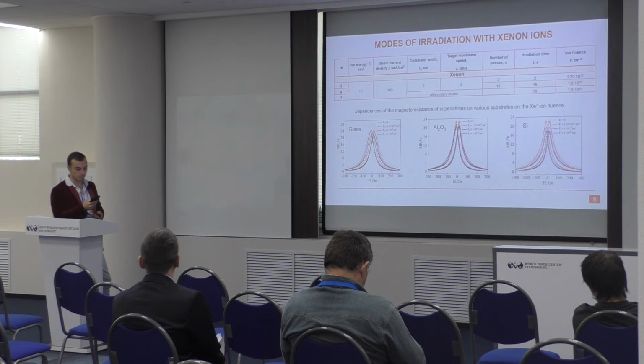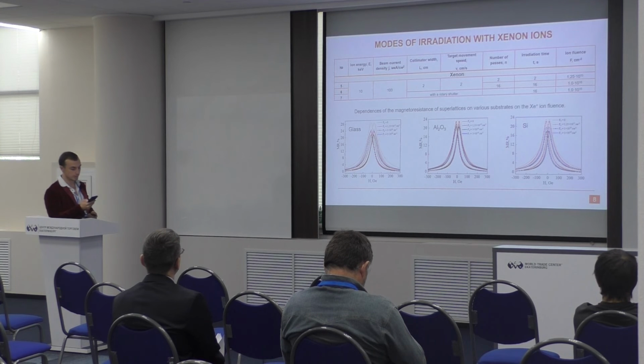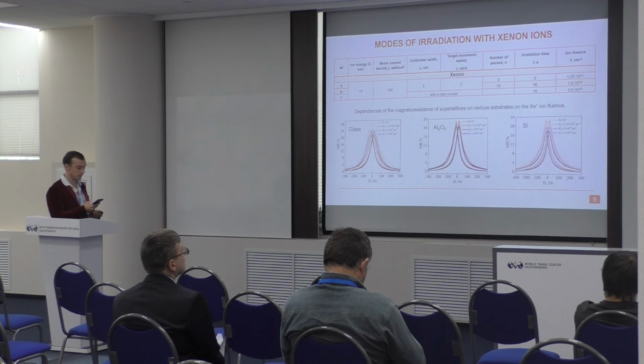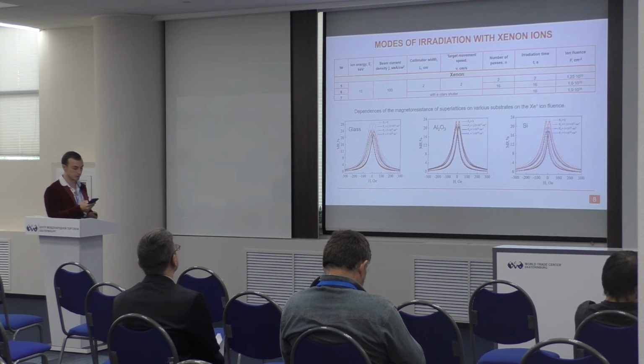The magnitude of the magnetoresistance hysteresis depends on the perfection of the microcrystalline structure of the superlattice layers, and it is known that these types of superlattices are annealed at high temperatures, which leads to an increase in the hysteresis due to an improvement of the perfection of the texture in the 111 axis. At low annealing temperature, such changes do not occur.